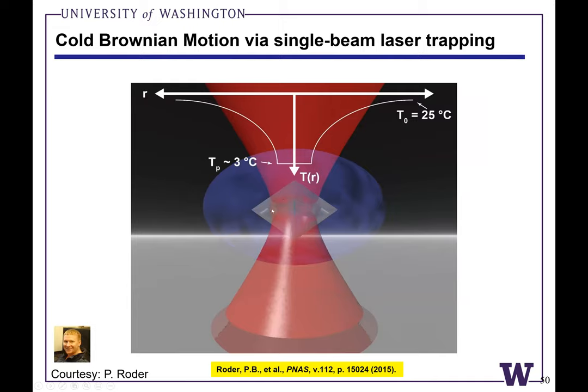My group first started looking at laser cooling materials in water. So this is an experiment where we had a single beam laser trap. We had a single ceramic grain in a laser tweezer, and we looked at the Brownian motion of this particle. And effectively, by cranking up the laser power, we could show that the diffusion coefficient of this particle went down instead of up in water. So this was a really exciting result, that we could effectively cool the particle to be several degrees, even tens of degrees below the temperature of the surrounding aqueous water bath.